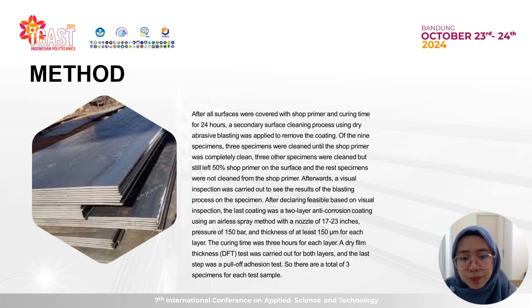After declaring them acceptable based on visual inspection, the last coating was a 2-layer anti-corrosion coating using an airless spray method, and the curing time was 3 hours for each layer. A dry film thickness or DFT test was carried out for both layers, and the last step was a pull-off adhesion test. So there is a total of 3 specimens for each test sample.